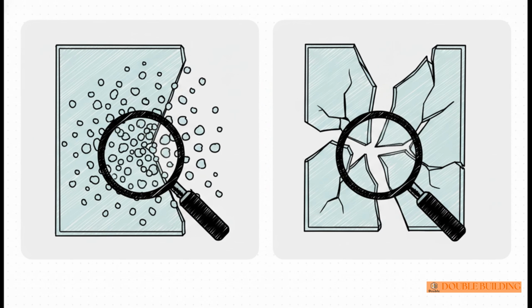This brings us to a really fascinating trade-off: fully tempered glass versus heat-strengthened glass. Fully tempered boasts a massive surface compression of at least 69 megapascals. But as we just learned, when it goes, it breaks into tiny granules.